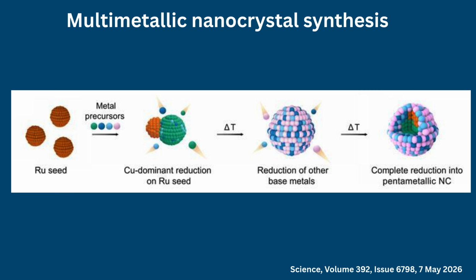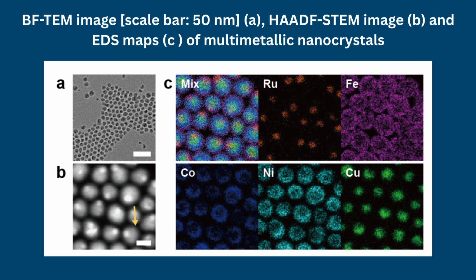The cooperative miscibility relationships among the metals promoted heterogeneous nucleation on pre-existing particles while suppressing independent nucleation events. This work demonstrated that carefully designed kinetic pathways can overcome thermodynamic incompatibilities between different metals. The synthesized pentametallic MMNPs exhibited catalytic ammonia decomposition rates nearly 4 times higher than pure Ru nanoparticles at elevated temperatures.